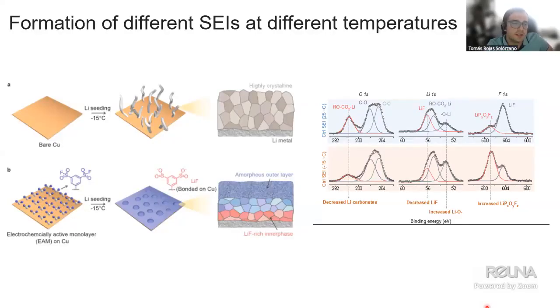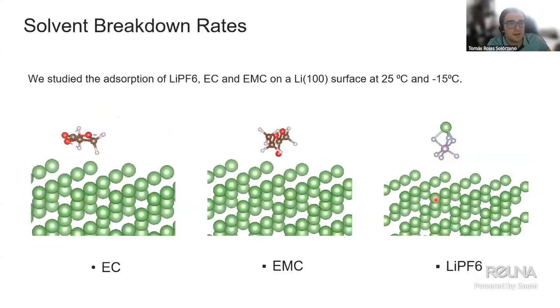So what they gave us in this case were different ways that they could build the anode, different ways of growing the surfaces of the batteries, and that will produce different formation or compositions of the SEI. And we wanted to complement those with as much information as we could on the composition of the SEI, maybe a more detailed one, and what could be predicted from the differences in the temperature. So what we started to look at was the electrolyte, which will be composed of these 3 components, LiPF6, EC, and EMC.